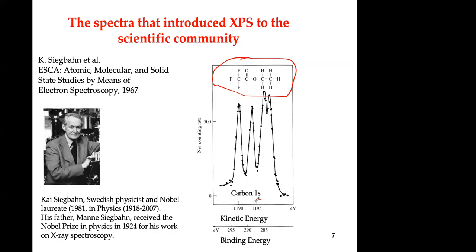you would expect to have only one energy for the electron from the 1s level, but he found out that you had four different energies, and those four different energies were due to the atom that was bonded to the carbon. Here you have hydrogen, and here you have fluorine, which is more electronegative. So it will attract the electron cloud of the carbon. So the carbon will have a positive charge. It would be more difficult to remove another electron, because you will convert it to a higher positive charge when you remove the electron from the 1s.